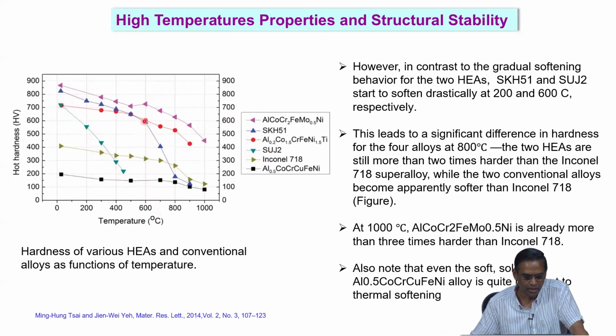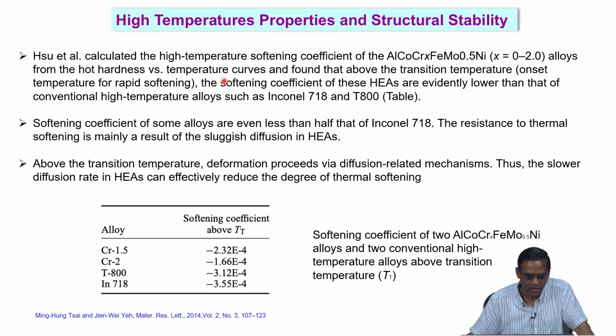So when you say the transition point, I mean this. There is a gradual transition, then an abrupt transition. So that is what is mentioned here. The softening coefficient for these alloys is evidently lower than that of the conventional high temperature alloys such as Inconel 718 and T800, as shown here. So you can see that the conventional alloys have a softening coefficient much higher than the high entropy alloys. The softening coefficient of some of the alloys is even less than half that of conventional alloys like Inconel 718. The resistance to thermal softening is mainly a result of sluggish diffusion in high entropy alloys. That is the belief as of now.